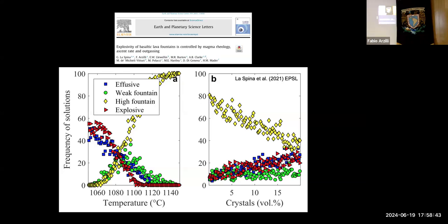And so when the temperature is quite high, high fountaining will be promoted, because at high temperature you reduce the undercooling, and so you slow down crystallization. If you start from a magma that is cooled down, so it means that it's cold in the magma chamber, you start already in a condition where the undercooling is quite high, promoting fast crystallization during the ascent. In fact, the frequency of solution for explosive eruption at lower temperature is quite high. This is important information for monitoring, for instance.